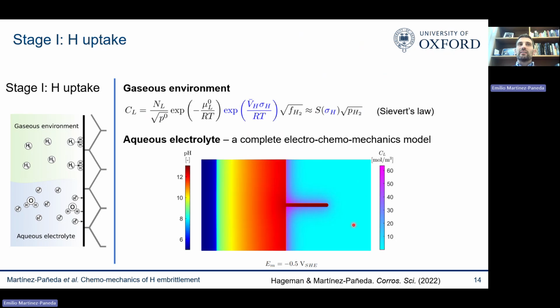So we can introduce the hydrogen to our samples using an aqueous electrolyte, which is much cheaper and easier. And then we can quantify for that aqueous electrolyte what is the equivalent hydrogen concentration. So if I go to my crack tip, I can input this here and then understand what is the equivalent hydrogen pressure, establishing a correlation between electrochemical and gaseous environments.